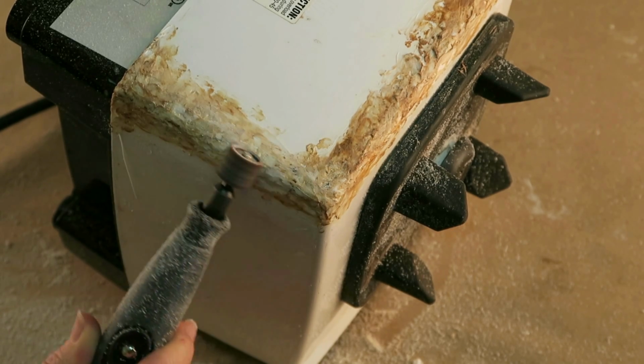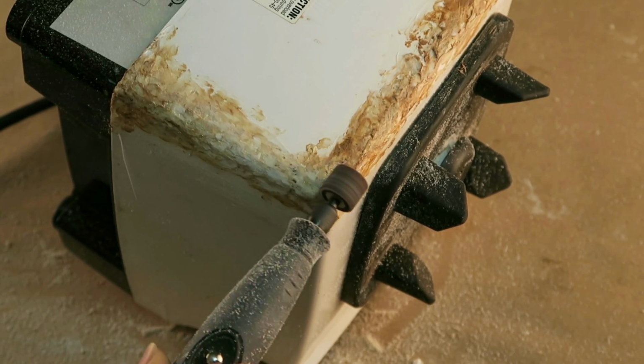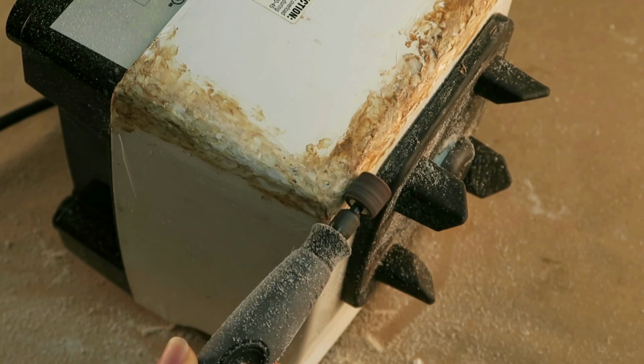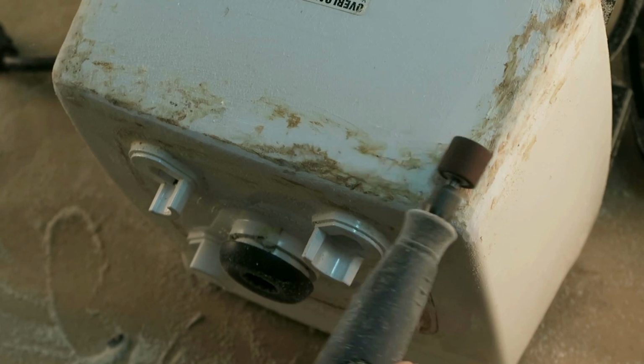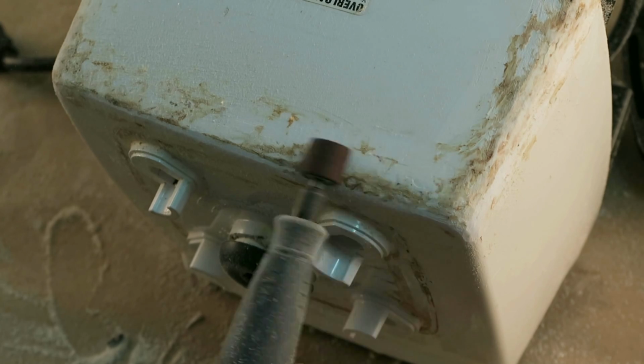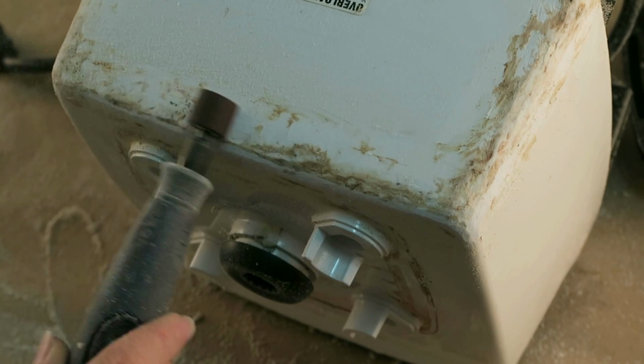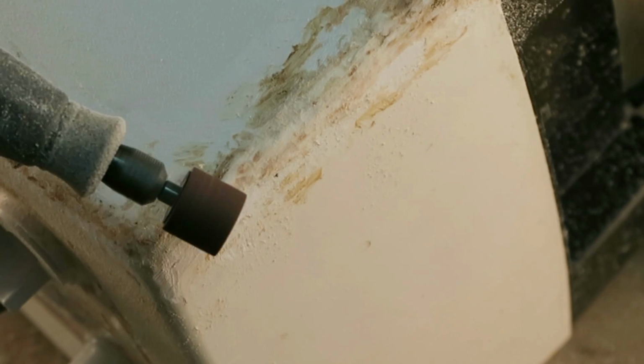After this revealing initial sand, I went back over all the seams with ABS filament and a hotter welder, really working it in this time in the areas that weren't bonded and not worrying about burning. The ABS weld is harder than the blender plastic itself, making it more of a challenge to sand the weld without removing too much of the parent plastic.